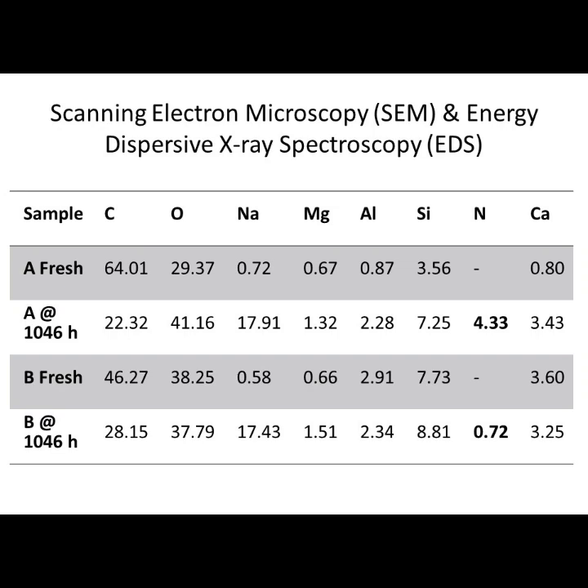Also, the silicon content was found to be higher for both aged samples, which could be because of the breakage of the Si-O bond in the glass fiber under the impact of the discharge activities. Finally, the content of metallic elements such as magnesium is increased because of the ionic exchange with the free hydrogen ions when the FRP rod is subjected to water or the nitric acid.